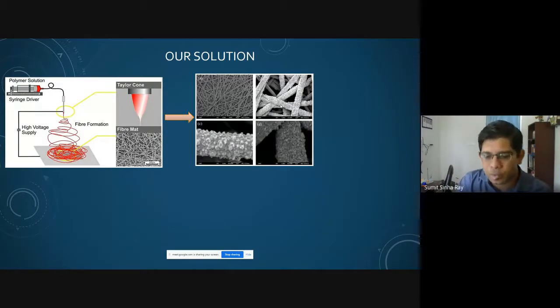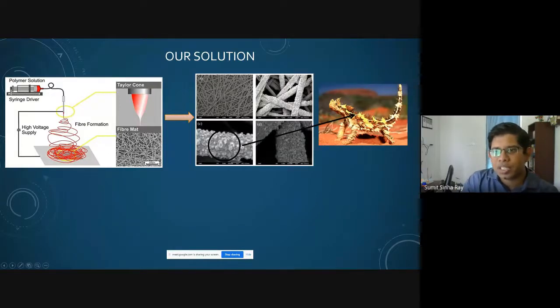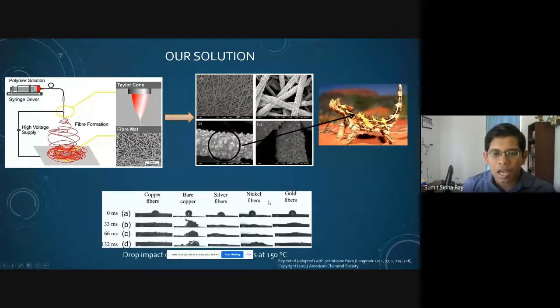The only trick is to tweak the structure in such a way that it mimics a kind of thorny devil structure. These thorny devils are called dragons practically, but they are not. They are lizards which have spikes on their back, and these spikes actually help them get moisture from the air, from an arid atmosphere. These spikes are hydrophilic in nature, and they allow nucleation to happen on them. So the same structure was mimicked here, and in normal gravity condition, when we tested at 150 degrees centigrade on a bare copper surface, the droplets tend to splash and form bags on the surface in the Leidenfrost effect. The nanofiber surface with metal plating actually allows wicking and enhanced heat removal.